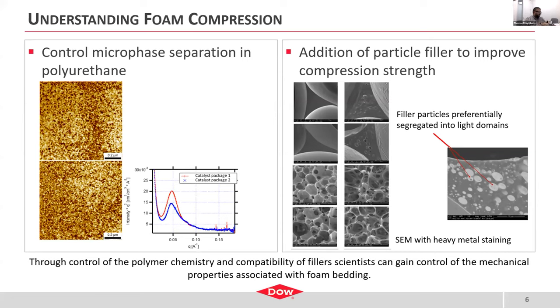Maybe a little hard to see that there's more, but the way we actually do know that there's more microphase separation is by the small angle X-ray scattering shown next to it, where you have a higher structure factor scattering from the distances between hard domains in the material that's being analyzed. So like I said, the amount of microphase separation as well as the average distance of microphase separation can change things like the compressive strength of your foam, and therefore how hard or soft your mattress is.